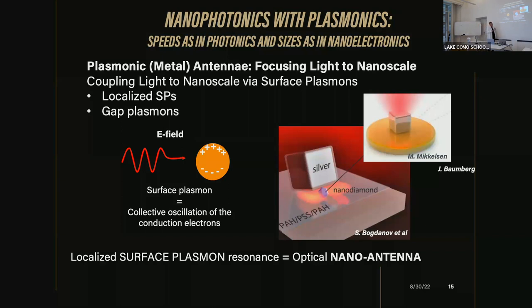Gap plasmons are excited in the electric gap between two metallic particles. Like in this case, epitaxial silver of the highest quality, which is actually provided by our Russian collaborators from Bauman University. And I should say that I have worked with silver all my life. I never saw anything remotely as good as what they produce. So in silver, single crystal nanocubes, and in between you have this gap. In principle, this gap could be as small as 5 nanometers, so you could have really dramatic confinement.